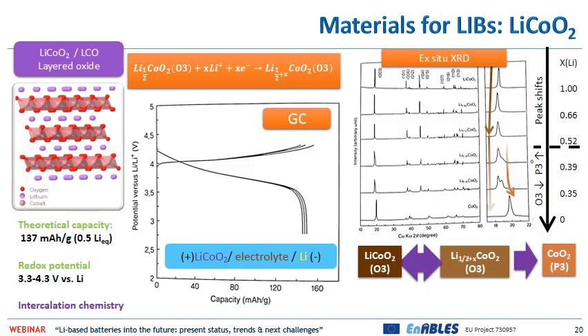The state-of-the-art material is lithium cobalt oxide. That is the material that is in all the smartphones and portable electronics. This material is a layered structure formed by octahedra of transition metal O6 units that are stacked within layers of lithium ions. The reaction occurs through an intercalation chemistry reaction that removes reversible lithium without altering the structure.